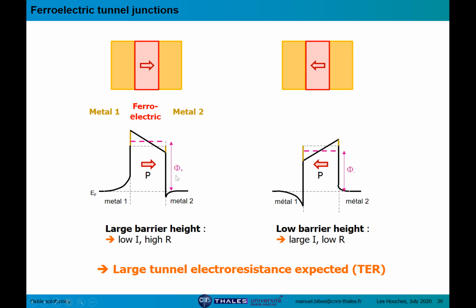So if you use two different metals, you will basically induce asymmetry, you will distort the potential profile by inducing an asymmetry that will result in a modified average barrier height, which is shown here with this dotted purple line. If now you switch the direction of the polarization, the asymmetry will reverse, and the value of the average barrier height will also change.